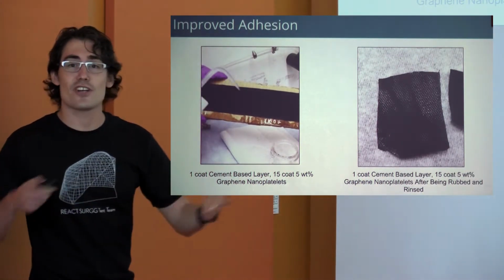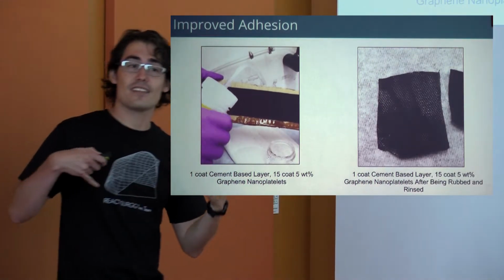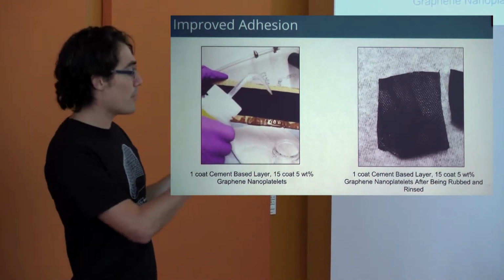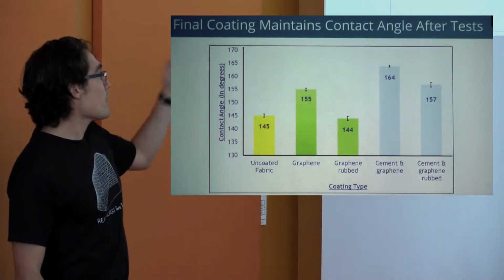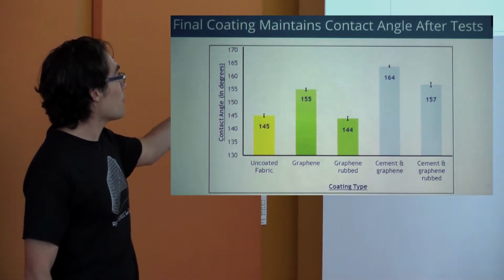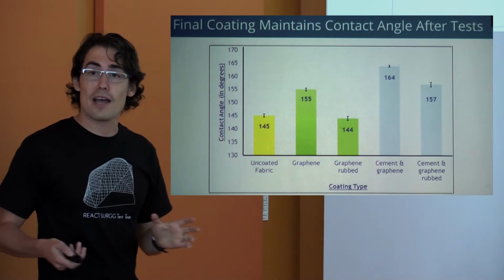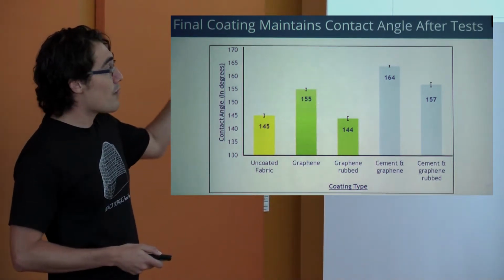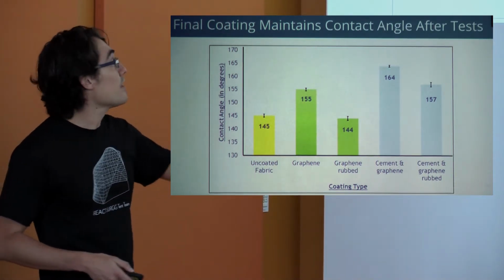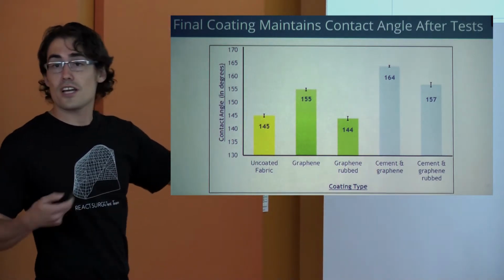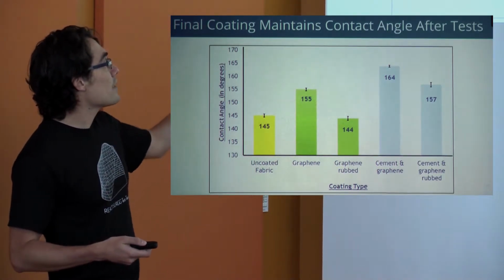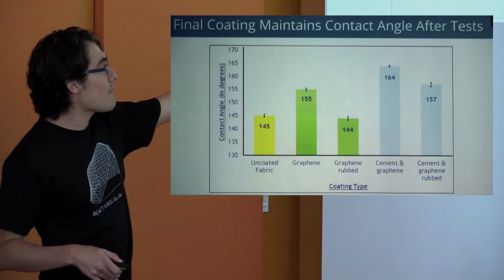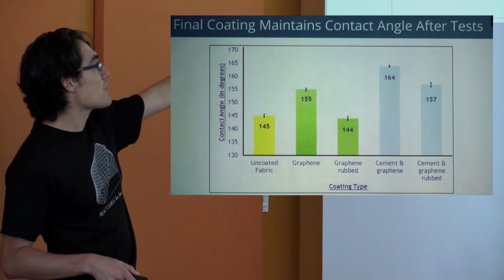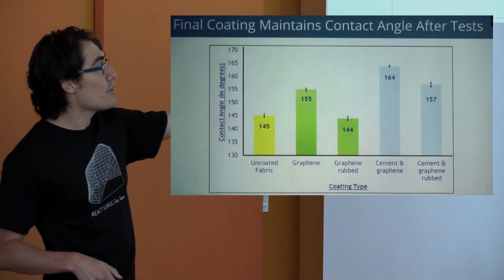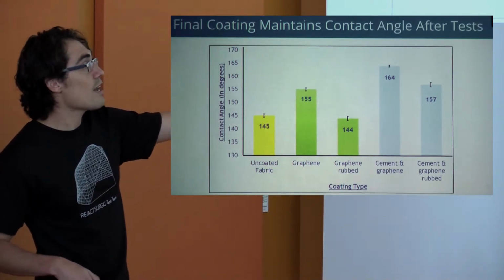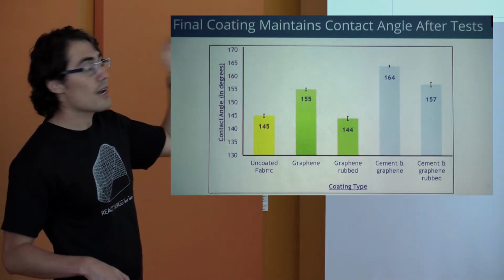But how much did it change, or how much better is it? That's something we could talk about a lot, but let me talk about numbers now. Here we have the uncoated fabric, which has a contact angle of around 145. And we can see that both the graphene and the cement with the graphene increase this contact angle, so it does make them more hydrophobic. But once they're rubbed, the graphene by itself is almost the same as the uncoated fabric. However, the cement and the graphene, even after being rubbed, maintains a super hydrophobic character.